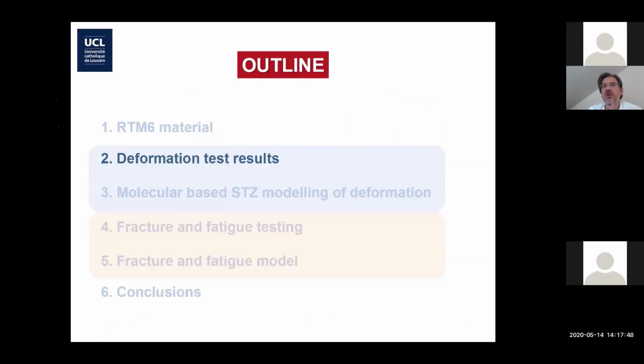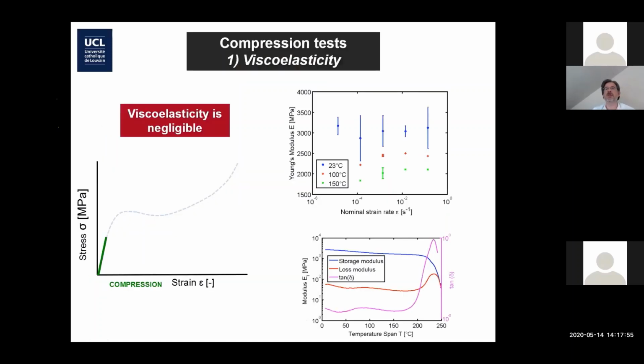Let me start by giving you an outline of the main characteristics of the deformation and strength of these materials. On the left, you see the schematic stress-strain curve, and on the right, some specific data. I'm starting with the elastic response, and what you see here is Young's modulus as a function of strain rate, almost no effect. And like I said here below, it's more important regarding viscoelasticity, storage modulus, loss modulus, which is very small. And so the viscoelastic effect of strain rate, for instance, on the Young's modulus will be quite limited for what I will discuss next.